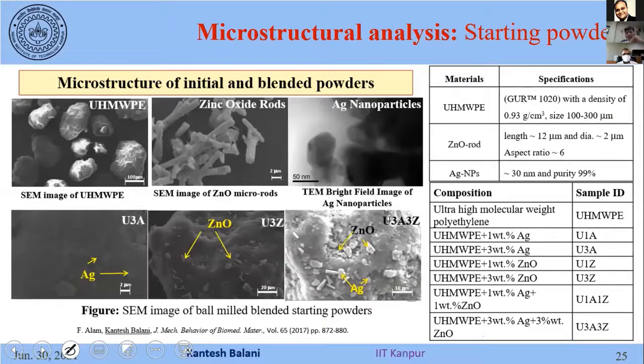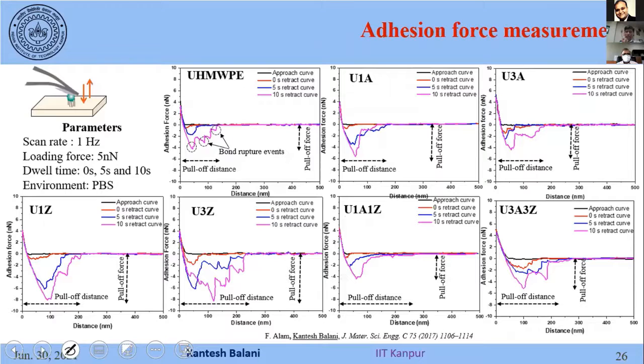So I will go a little fast here. I would like to give more time also for any discussion. So we have taken this polymer because we realize that it is becoming good. We have added some antibacterial agents like silver and also zinc oxide. Why and what, we will discuss later on. And again, we see this profile of load displacement or adhesion force and distance, how things are being changed with respect to the attachment and de-adhesion of the bacteria from the polymeric surface.